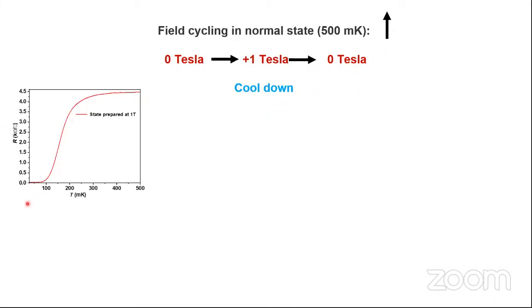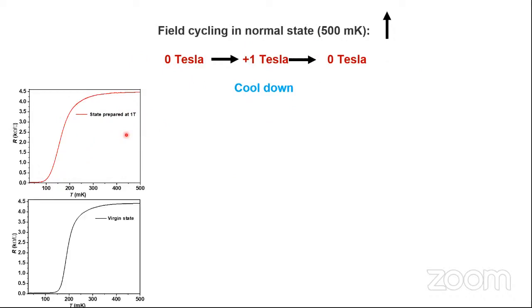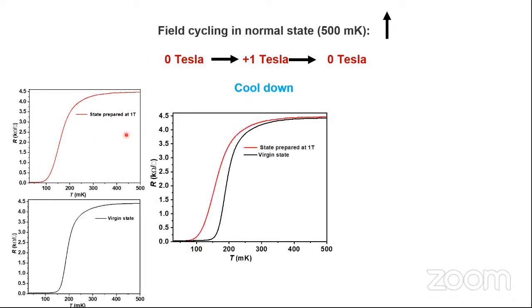has gone down. This is what I call the state prepared at 1 Tesla. When I say that, I mean that I have done a 1 Tesla field cycling, 0 Tesla, 1 Tesla, 0 Tesla, and then cooled it down and found that the critical temperature has gone down. If I compare this with the pristine state, then this is what it looks like. This is the pristine state data, and the red line shows the transition after doing the field cycling in the